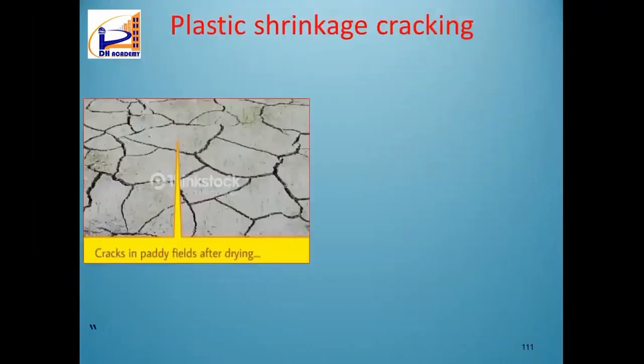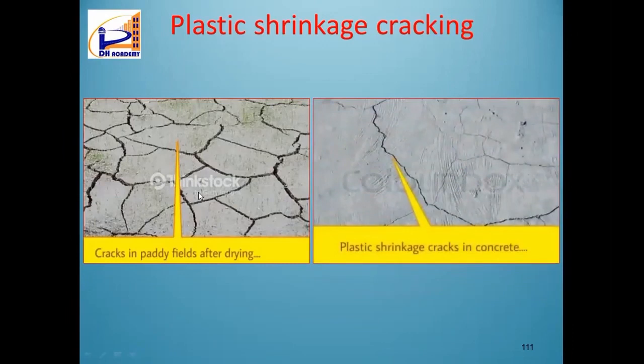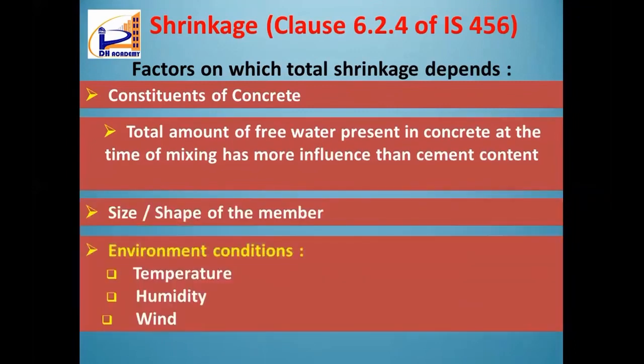And if this evaporation happens from the concrete, then what is the problem? The problem is plastic shrinkage cracking. You can see the picture. It is a photograph of a paddy field. You can see these cracks. Why did this crack happen? Because earlier there was water, and because of the hot sun, that water evaporated, and that evaporated area came as cracks, right? Similarly, plastic shrinkage cracks in concrete. The main reason is that water evaporated, and because of that these cracks happen. And in the IS code, it is mentioned in great detail.